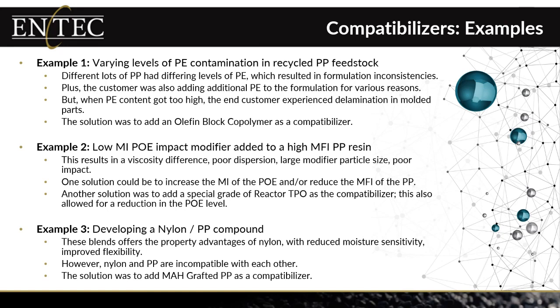So in this case, we have a special grade of a reactor TPO that makes a very, very good compatibilizer for low melt index POE impact modifiers and high melt flow polypropylene, like for example, a 50 or 55 melt flow polypropylene. So again, this is a case where that particular reactor TPO as a compatibilizer would outperform the olefinic block copolymer or some of the other compatibilizers I had listed on the previous page.